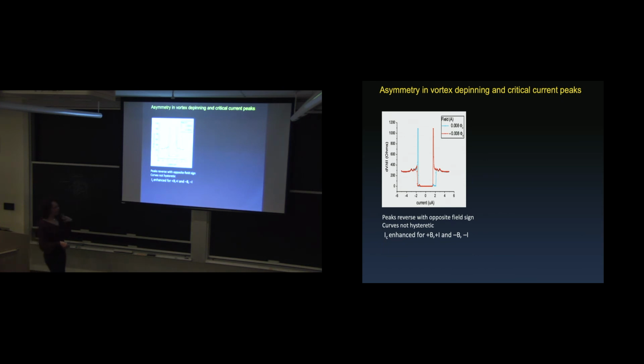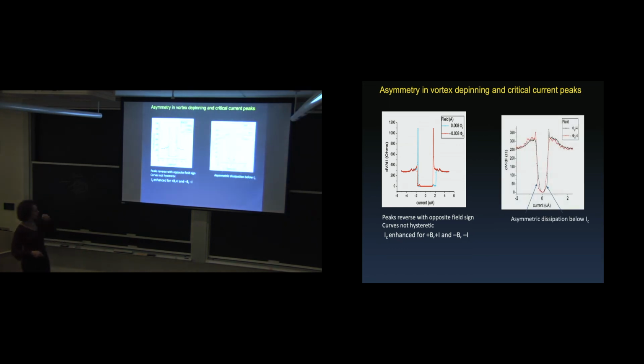And so on the topological material, something we don't see in other materials is an asymmetry between the direction of the field and the direction of the current. They seem to be correlated, in when we get peaks and how high the critical current is, which tells you that pinning and depinning are somehow influenced by dissipation in the topological surface, which is consistent with this sort of surface spin-momentum locking. And same thing, you can see we get different types of dissipation. If you measure the width of your critical current, you get different values depending on whether you have positive or negative field or current values.